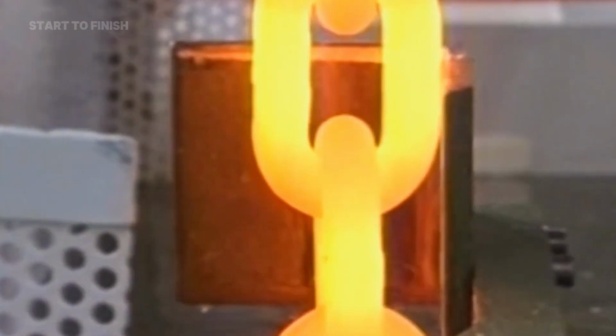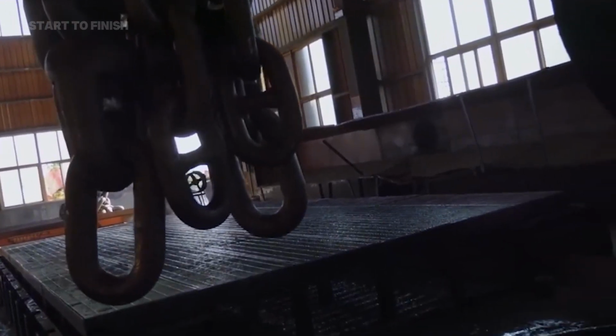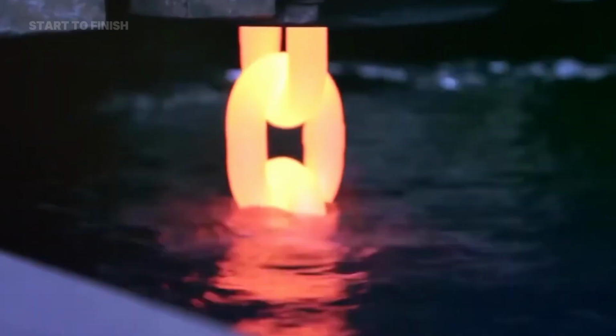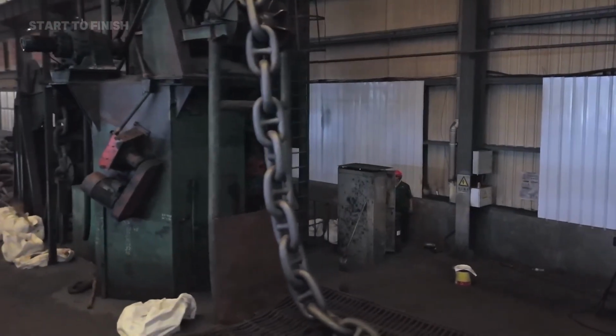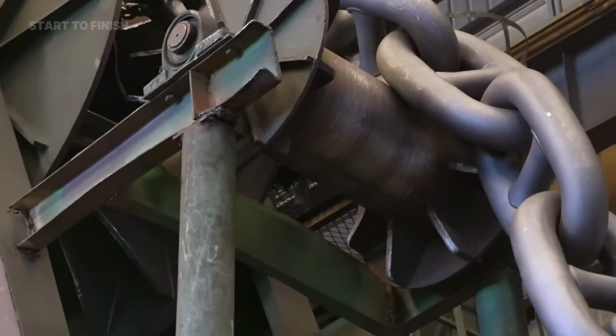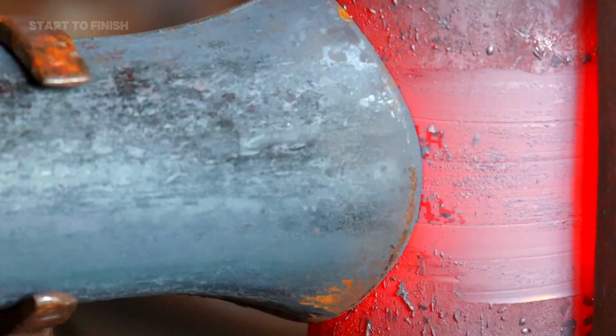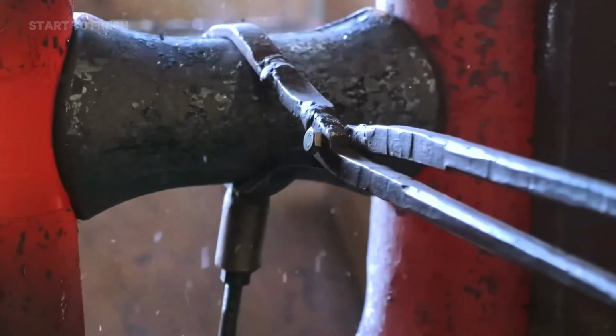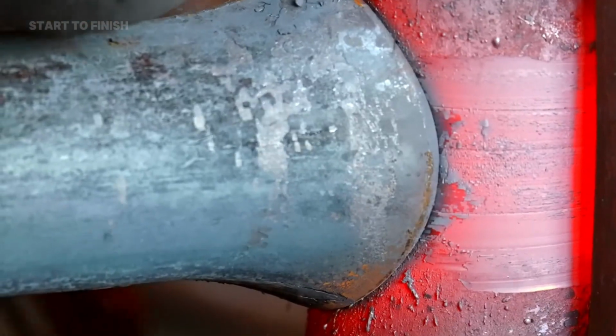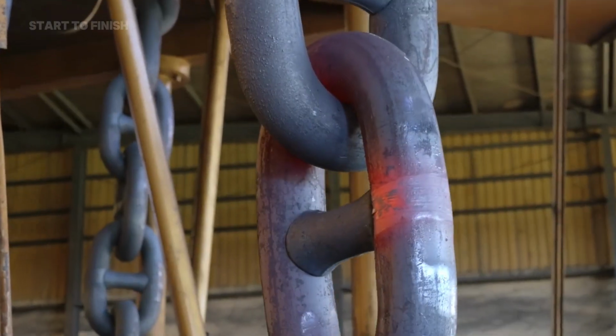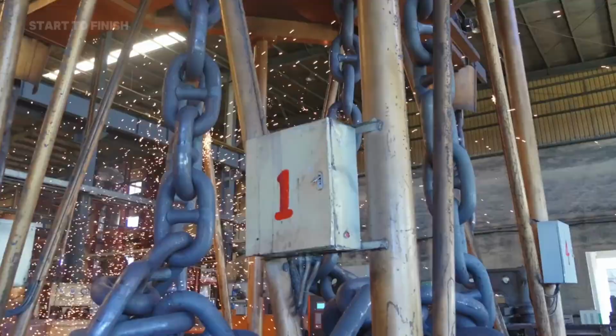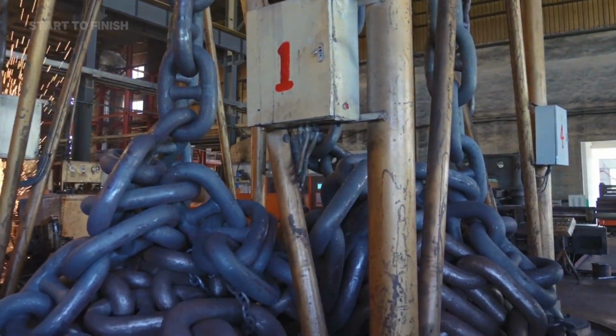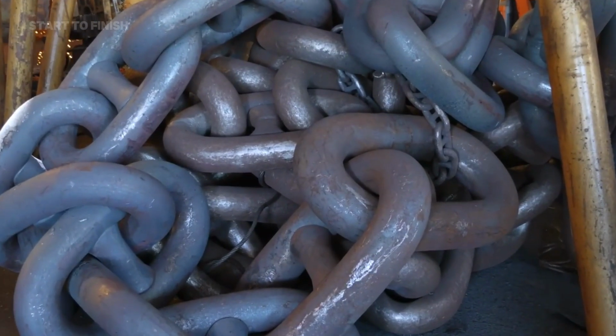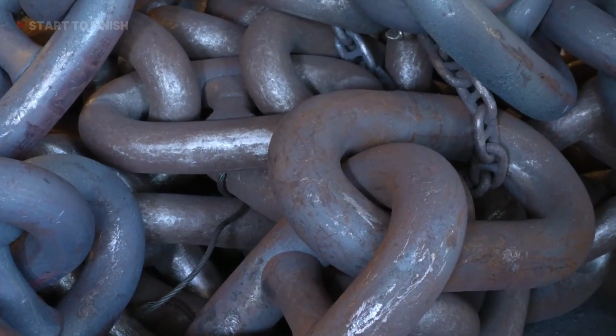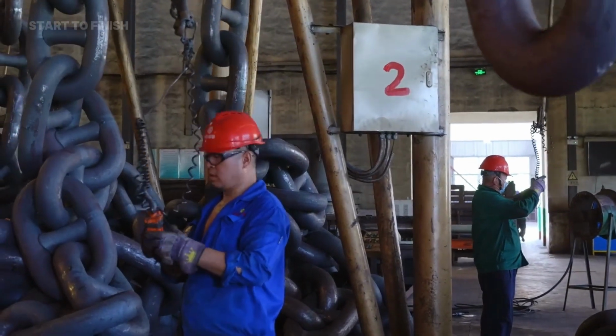beneath the waves. Immediately after heating, the chain is quenched in massive cooling tanks filled with temperature-controlled water or oil. This sudden drop in temperature hardens the steel, locking in the new molecular structure. Each link is then tempered, reheated at a lower temperature to balance hardness with flexibility. Too hard and it could shatter under stress, too soft and it would deform. This combination of heat, quenching, and tempering ensures the metal achieves its ideal balance of tensile strength and elasticity.